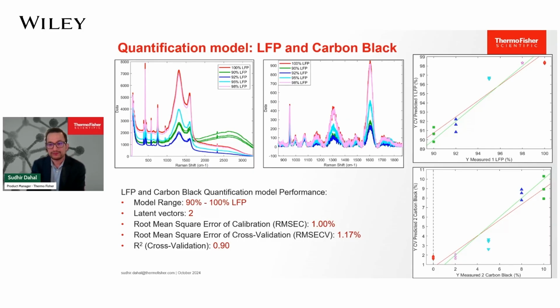To enhance the robustness and extend the range of the model, additional data is always preferred, and it can be incorporated as needed to further refine the model based on the need. Therefore, the process Raman analyzer has demonstrated its capability to monitor and quantify the concentration of lithium iron phosphate, which is an important compound for lithium-ion battery manufacturing.